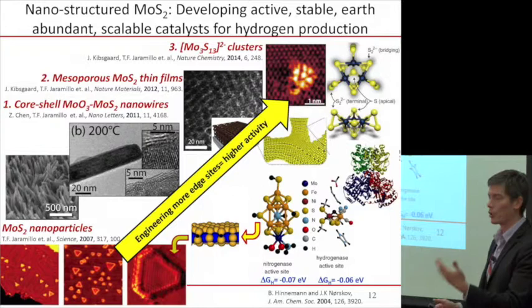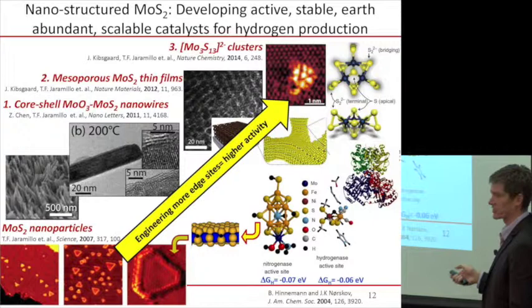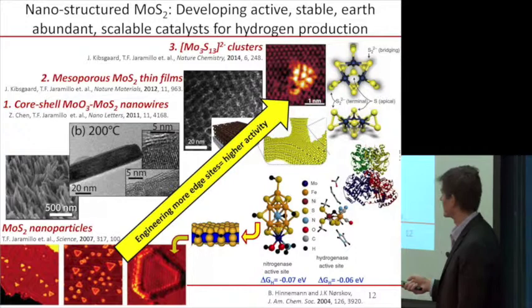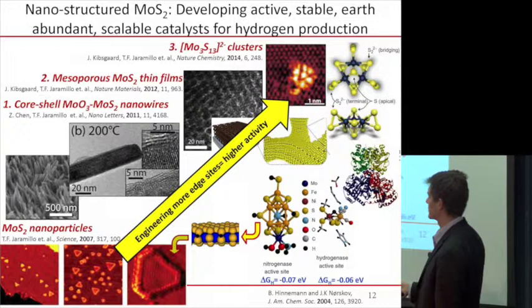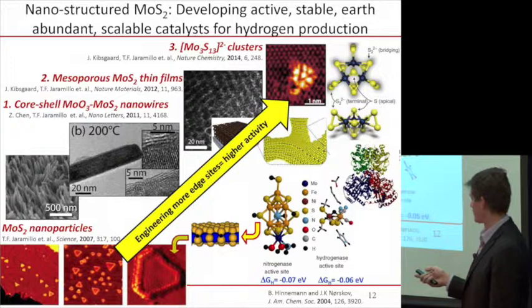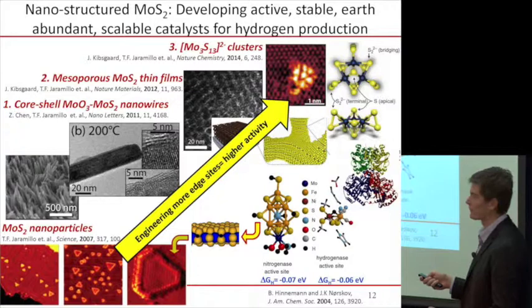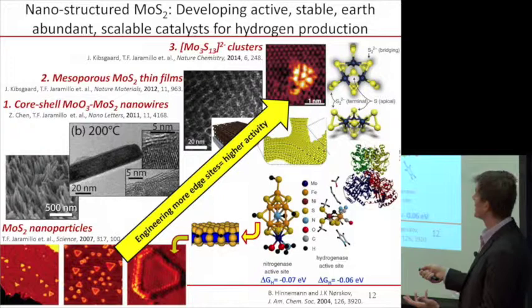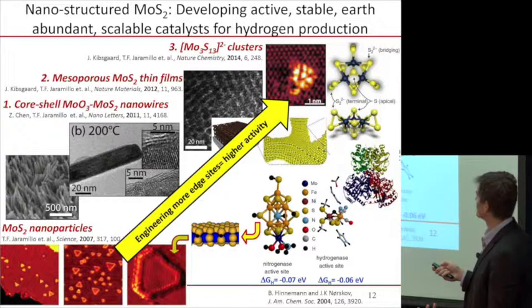Long story short, they had used these calculations to suggest that certain types of materials that contain no precious metals might work similarly. And indeed, when I was a postdoc working in Denmark, we were able to synthesize some of these types of nanocatalysts and showed that, in fact, they were very effective. These are molybdenum sulfide materials. They were very effective for hydrogen. When I started my group here at Stanford 8 years ago, we started cranking out all kinds of different high surface area catalysts of molybdenum sulfides with lots of edge sites, which is where all the action takes place. So nanowires and nanoporous materials and small molecules, basically lots of edge sites means high activity.